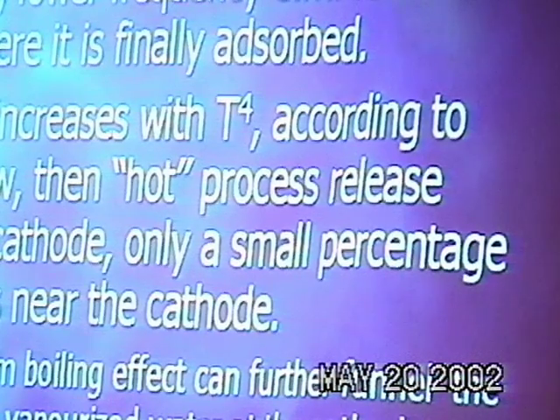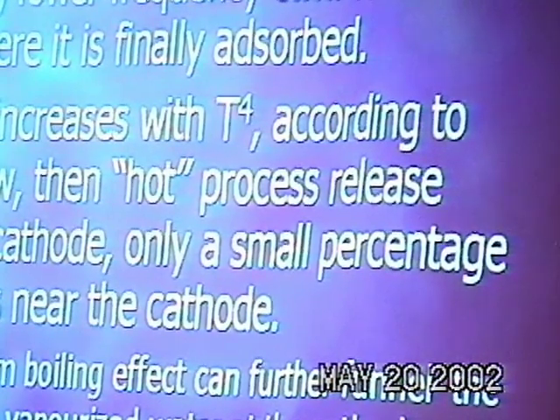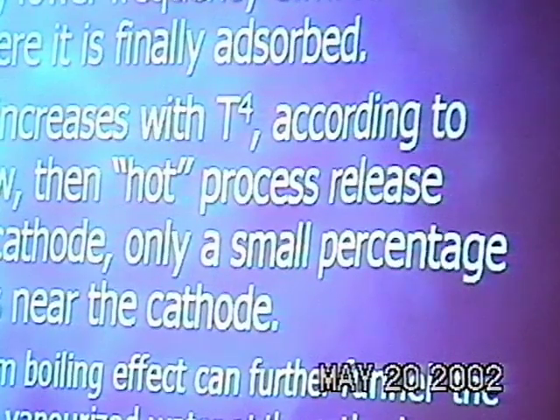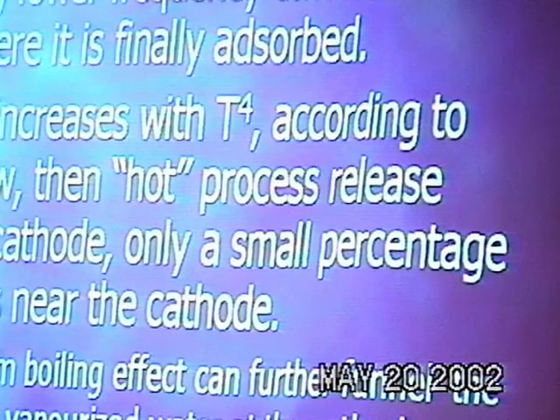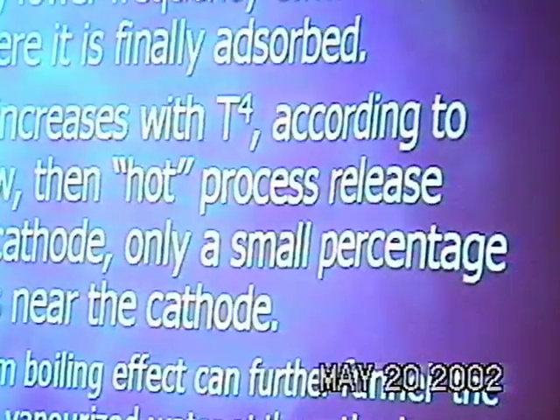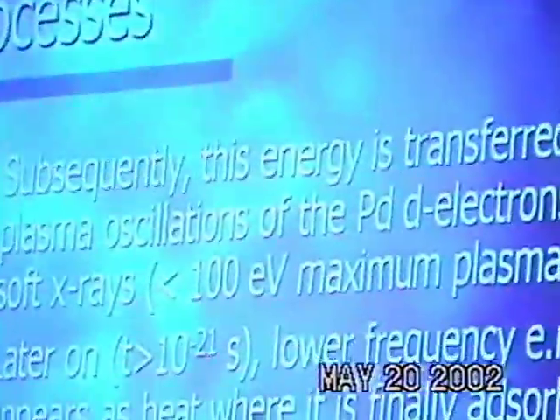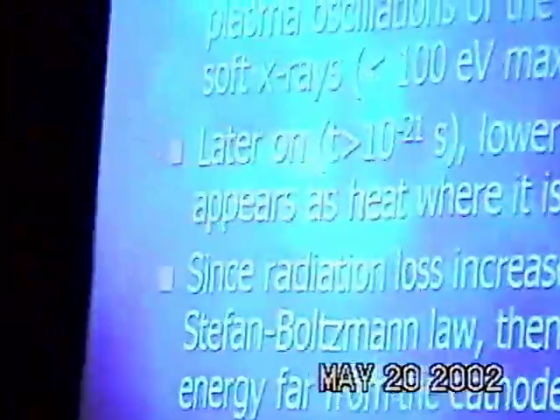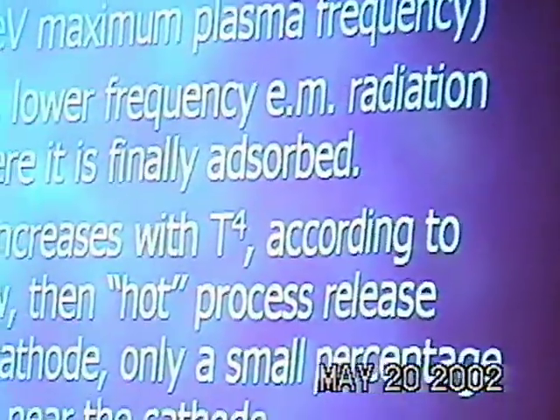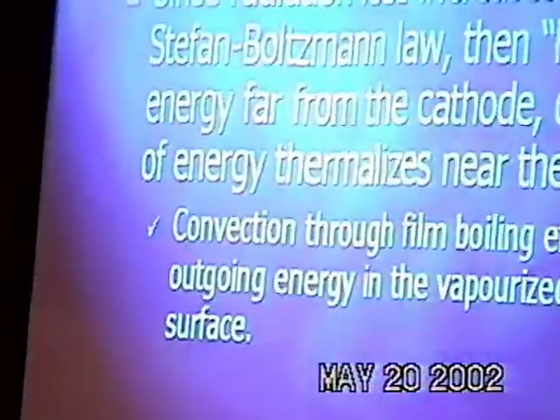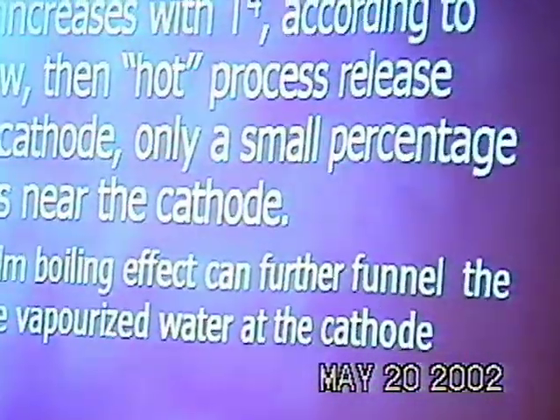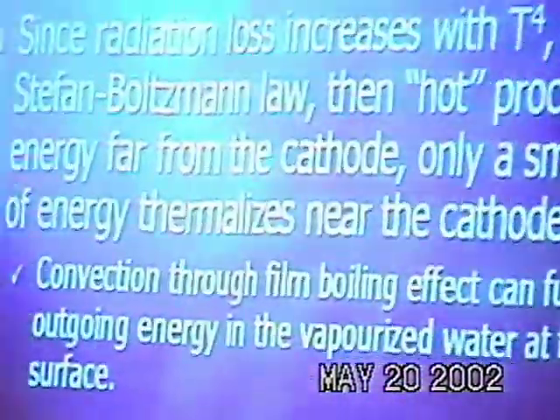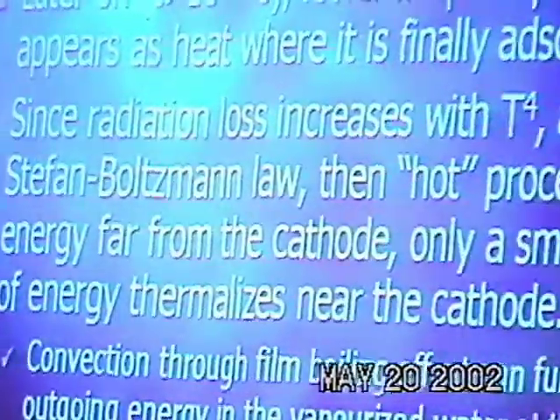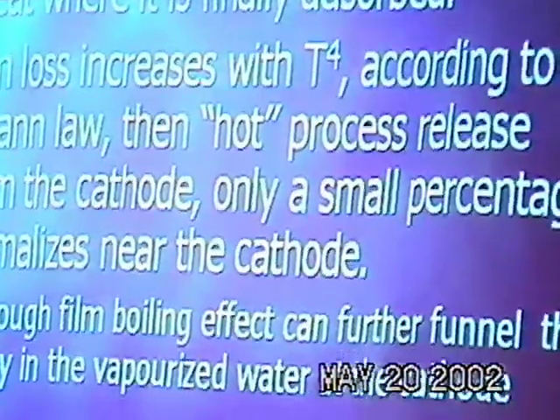They can receive this energy, and they can eventually release it in the form of X-rays, and the maximum energy is 100 eV. It is the maximum plasma frequency of this particular class of electrons. And then starts the cooling of the process. This is a very hot process. A nuclear process is a very hot process. So what we learned by thermodynamics is that radiation loss is proportional to T to the 4. It is a very hot process, so the main channel of the thermalization is via electromagnetic radiation.